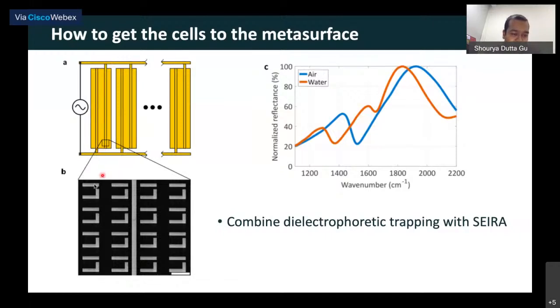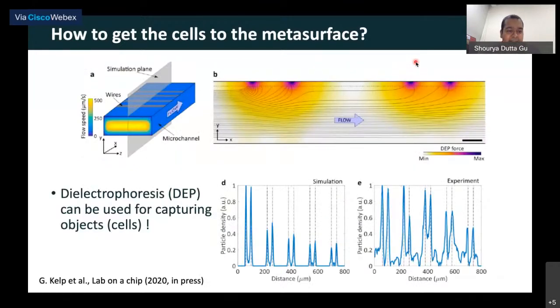and this is a typical SEM image. So we have the same structures as before, and these are the wires that we use as electrodes, right? Now, if we send light and look at the reflected light as a function of wave number, shown here, we again see a similar feature, a resonance here and a resonance here, right? Now, if you simulate the response of the electric field and calculate the forces, which is what we did before we did the experiment, you can do this using COMSOL, as shown here.